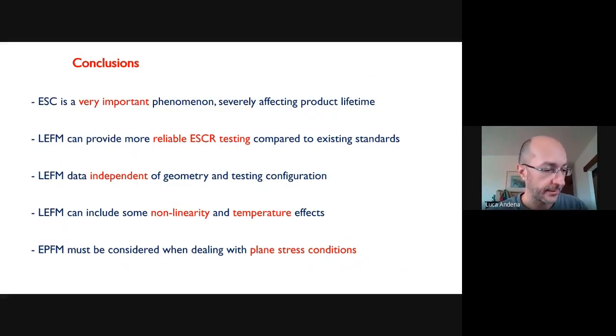Okay, now I will run a bit fast probably, but I think I have some time to point out some conclusions. I hope that with this short lecture, I convince you that environmental stress cracking can be a very important phenomenon, because we've seen that it can really decrease the expected lifetime of some products by orders of magnitude. So it's very important to find out whether the polymeric material chosen in a given application can be affected by the environment. Of course, this doesn't apply if the environment is in contact while the material is not loaded, because you have to keep in mind that only when you have the simultaneous presence of the environment and the mechanical loading can ESC occur.